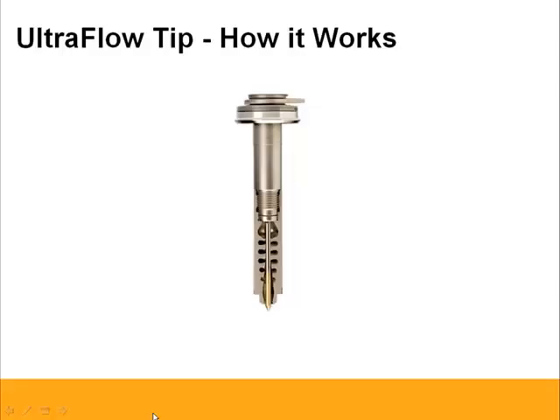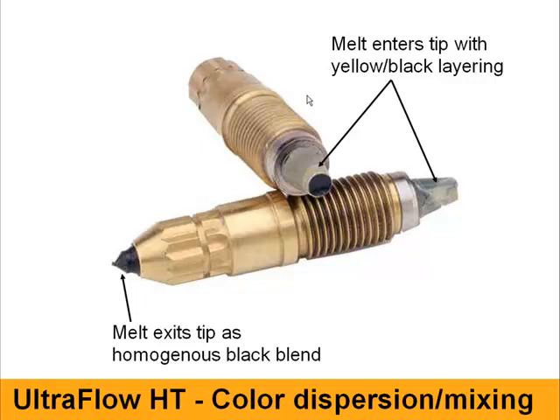So what does that do? I'll show you an example here. This is again a tip pulled with frozen material at the end. You can see this was a change from yellow to black. Most of the yellow is already gone, but on the boundary layer we still have some yellow material left over at the entrance of the tip. Now as we exit the tip on the front, you can see that layer is gone. It's basically mixed under. It's within the black material now. It's hidden. It's within the matrix. And that's one way you can speed color change. You don't really eliminate it, but you make it disappear for the eye.